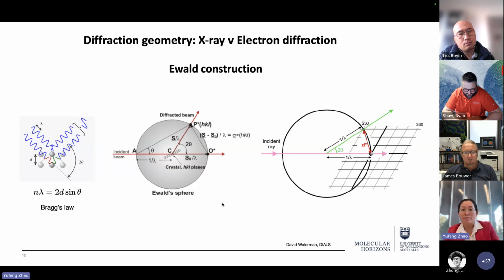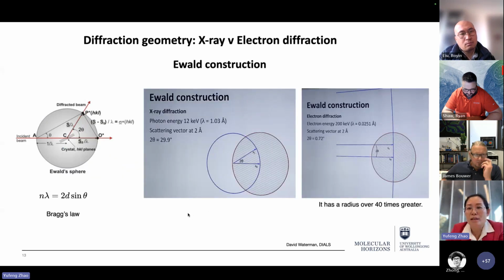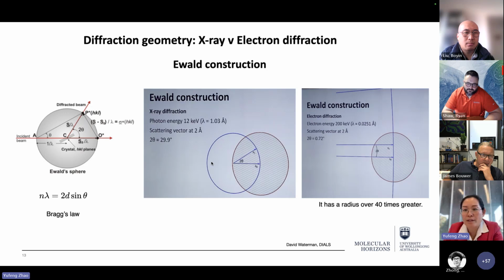So what's the difference between X-ray and electron diffraction? For example, for X-ray, a standard machine with 12 keV has a wavelength of 1.03 angstrom. For a scattering vector at 2 angstrom resolution, the 2 theta is about 29.9 degrees. The Ewald sphere would be a really complete sphere, with the detector very close to the crystal. But electron diffraction is also diffraction, and it also has to satisfy Bragg's law.